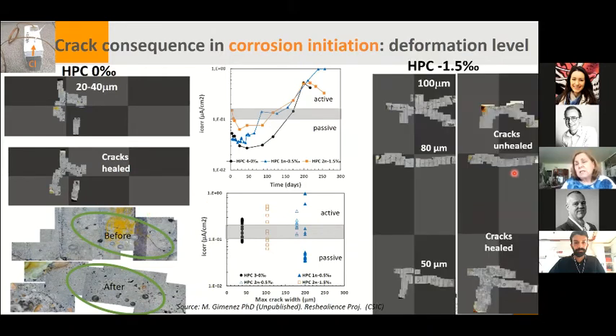With higher deformation, the crack is larger, and we can have some healed cracks, but some others will be unhealed. And finally, the corrosion is initiated. This is before, and this is after exposure.